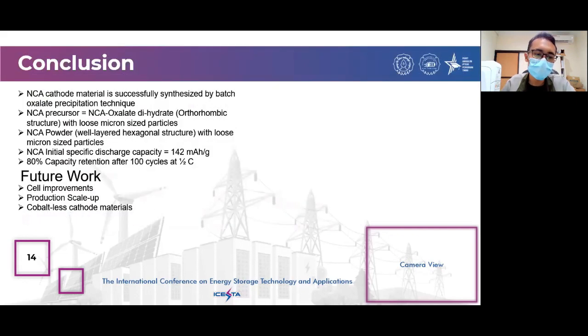A simple oxalate precipitation technique was successfully applied to produce the NCA cathode material of lithium-ion batteries. Based on the XRD and FTIR analysis, nickel-rich oxalate precursor was successfully formed by the reaction of a solution containing nickel, cobalt, and aluminum ions with oxalic acid. After the heating process, a highly crystalline NCA powder with good structural property was obtained, which was confirmed by XRD and FTIR analysis. The initial discharge capacity of the obtained NCA was 142 mAh per gram, measured at the charge discharge current of 0.1 C.